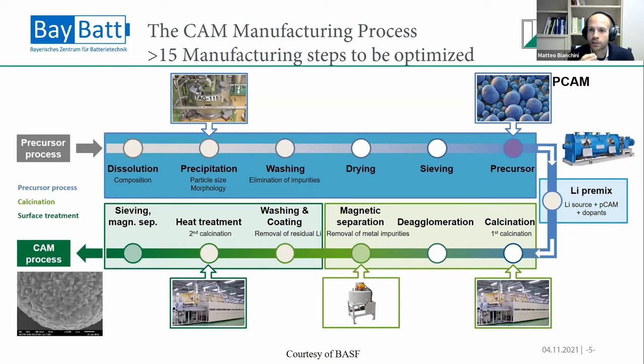And this is an incredibly important step because it's what will generate the morphology, especially the secondary particle, but also primary particle level of this PCAM, the precursor of the cathode active material. So this hydroxide will have a given morphology, which is decided for the most part during the precipitation. And then we have some additional steps of drying and sieving and washing.